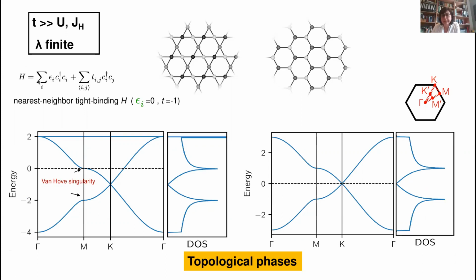My electrons are basically described in terms of a kinetic energy with this tight binding energy and this on-site energy. By just solving this Hamiltonian, which is easy to solve because it's just a one particle Hamiltonian, if we look at the corresponding band structure for these two lattices, starting with the honeycomb lattice, we find very rich features. This is two sites per unit cell, so we get two bands, and depending on the filling of our system, we have Van Hove singularities, which show an infinite density of states.